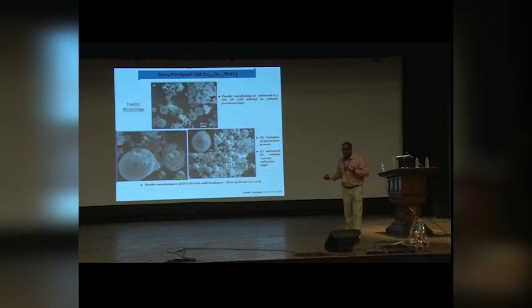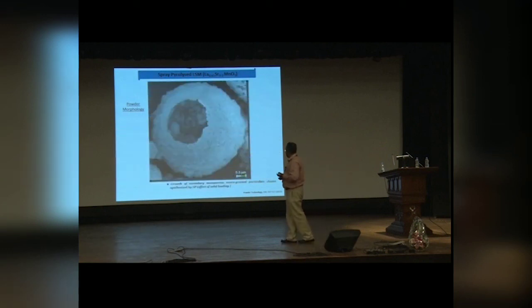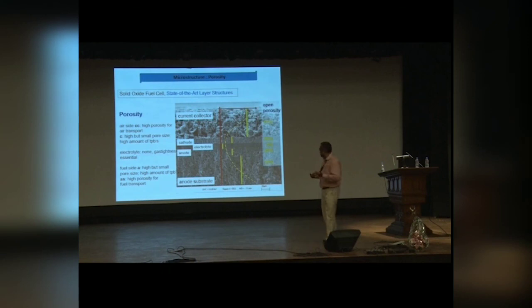Yeah. So you need to have this type of powder morphology. You have to control your powder morphology by controlling the kinetics of your powder making technology, and we did that because in some cases you need to have the powder in such a way that it has to be porous or it has to be core shell. Suppose, for example, this is the microstructure. These all are basically nano powders, and there is a hole. There is basically the porous microstructure. So this type of material one can introduce in this solid oxide fuel cell and can achieve very high performance.